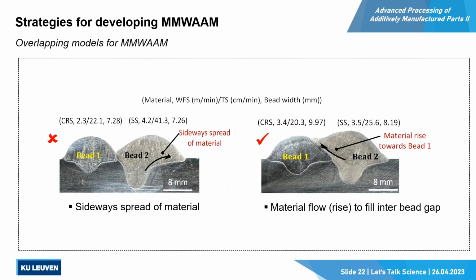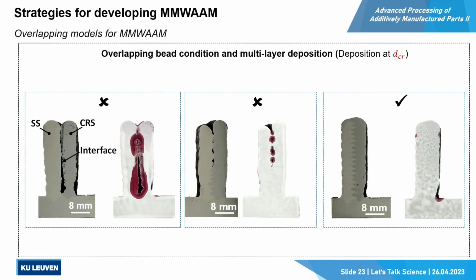But with a slight change in the offset distance between these two beads, we can have a material flow from bead 2 to bead 1 to have a complete fusion. With this model, we try to find the proper offset distance, which we call the critical offset distance, to have an optimum surface on top and also a complete fusion between materials. In the next slide, this offset distance has been compared to the other models.